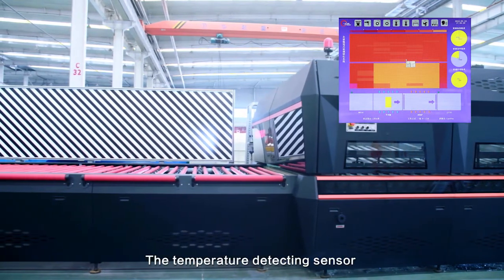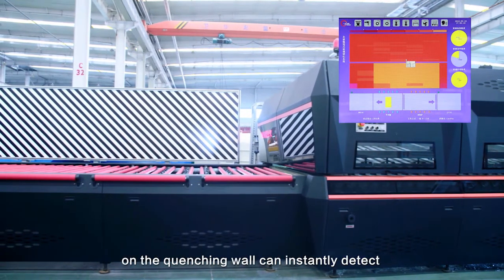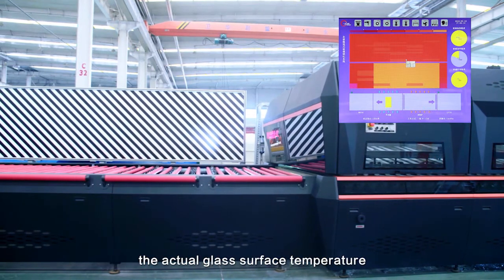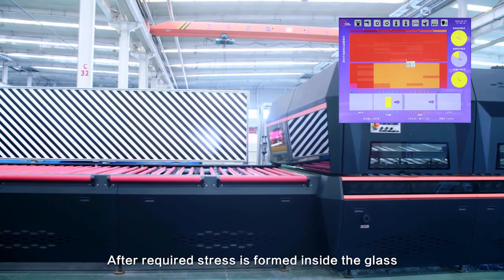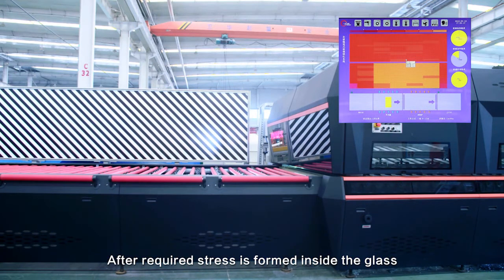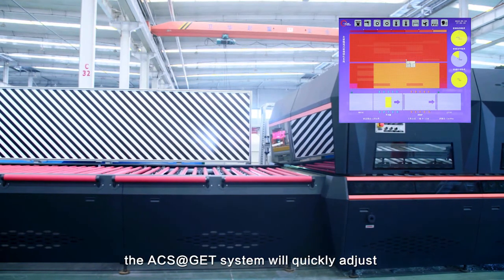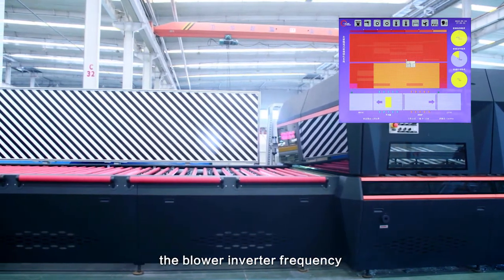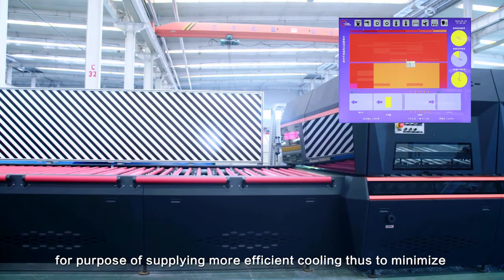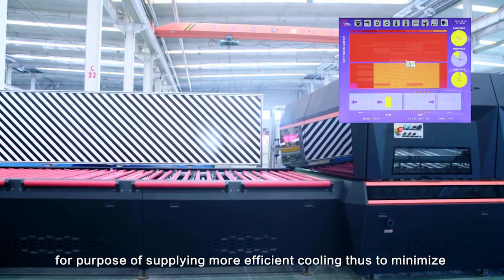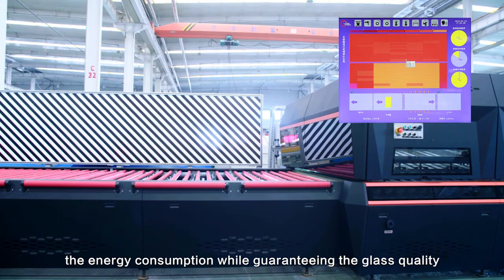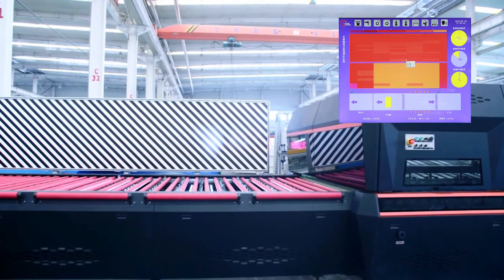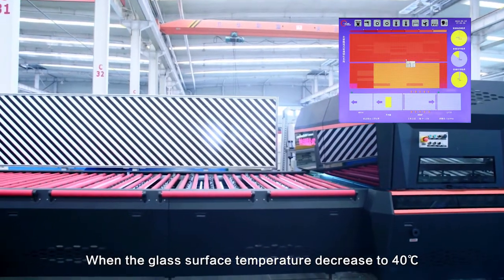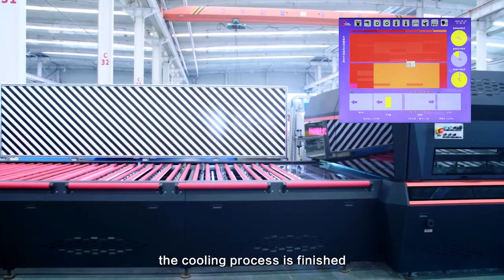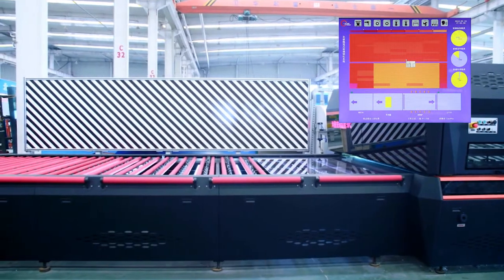The temperature detecting sensor on the quenching wall can instantly detect the actual glass surface temperature. After the required stress is formed inside the glass, the ACS at GET system will quickly adjust the blower inverter frequency to supply more efficient cooling, thus minimizing the energy consumption while guaranteeing the glass quality. When the glass surface temperature decreases to 40 degrees Celsius, the cooling process is finished.